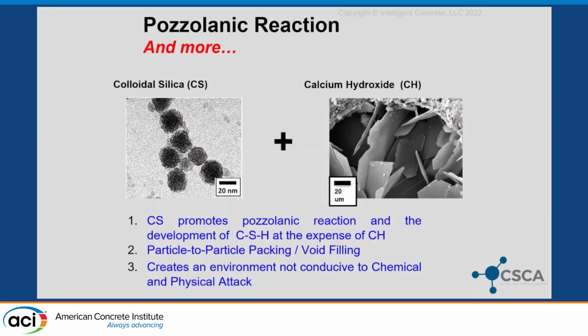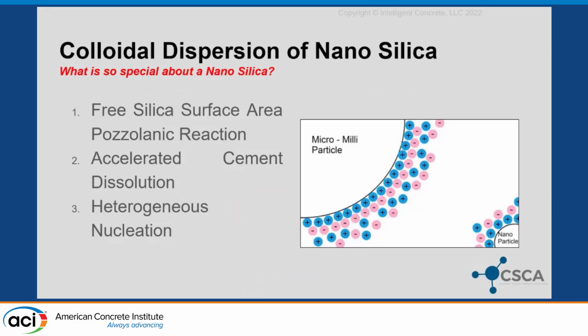It promotes pozzolanic reaction, the development of more of that backbone of concrete strength through the consumption of calcium hydroxide. We have particle-to-particle packing. We have void filling. All these things create an environment where the concrete is less susceptible to physical and chemical attack. And what is so special about it? We've got these really fancy terms. First one is easy. You've got a really small particle that's really reactive. Your pozzolanic reaction takes off like a bat out of hell.